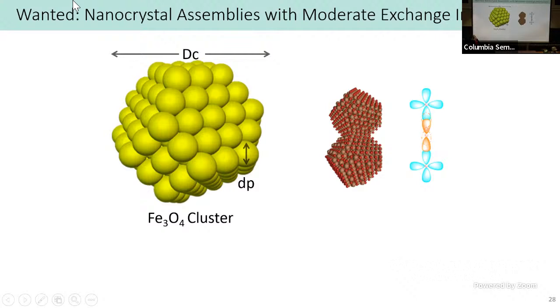But our approach to making it porous is to cluster. So each of these yellow balls is a single crystal, but those single crystals are oriented and attached during their formation process. And in doing so, they're very oriented across. So it's like they're all pointed the same way crystallographically, but they have holes where they're not perfectly cemented together. If you're able to achieve that, you can get very, very high susceptibilities.